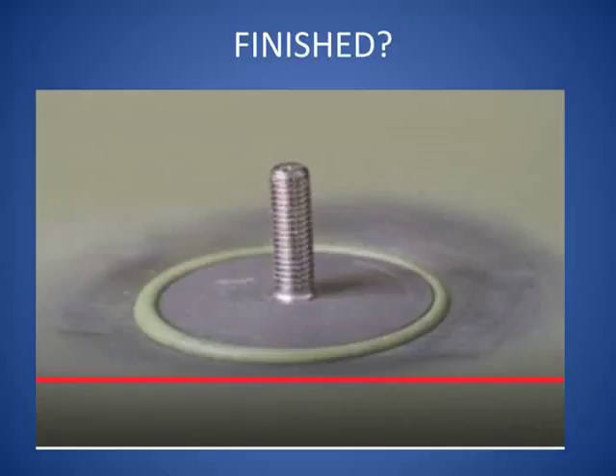The reason I put the question mark on the finish there is part of this is the surface prep. You can see where what looks like a primer, a weldable primer, has been sanded and ground away so that you have a clean surface to bond to. So you get a better bond. You get a better bond to a sanded steel surface than you do to paint. If you're using a lower loading requirement, you could just stick it to the paint. Then the strength of the adhesive is most likely the strength of the paint. That might be all you need. Here you still have to repaint.